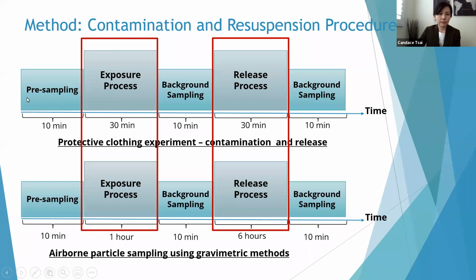We do pre-sampling, then measure the exposure, hold for a little bit, then measure the background before we do the release. This is the purging time I mentioned - we clean the air out after exposure, then start shaking the mannequin to measure the resuspension of nanoparticles from the lab coat, and then collect background sampling for comparison.